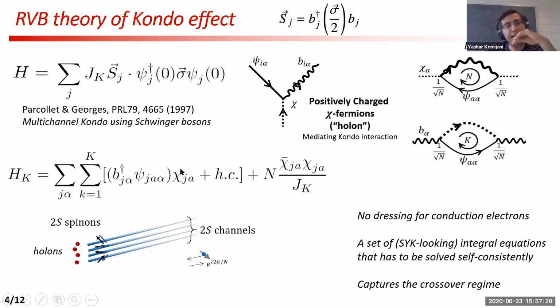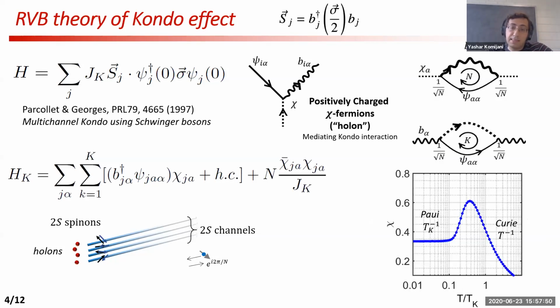As a result of this interaction, the propagator of the holons and the spinons will become dressed by these bubbles. But there will be no dressing for the conduction electrons because they carry 2 index. So in these 2 types of diagrams, these will remain bare. And this will give me a set of SYK looking integral equations that we can solve self-consistently to follow this evolution from the crossover from the UV to IR. For example, this is the susceptibility that can be extracted from this type of calculation, which shows a crossover from a Curie to a Pauli susceptibility.